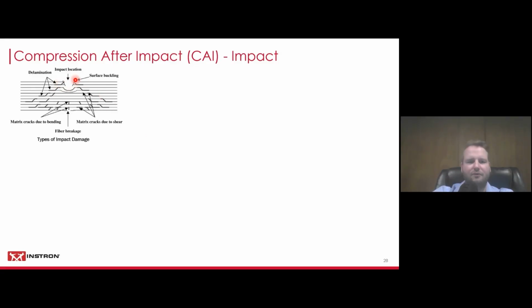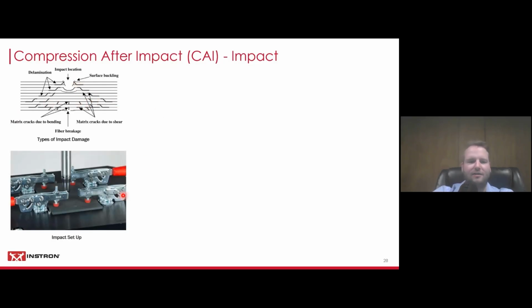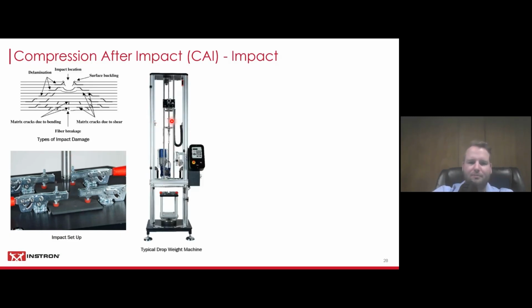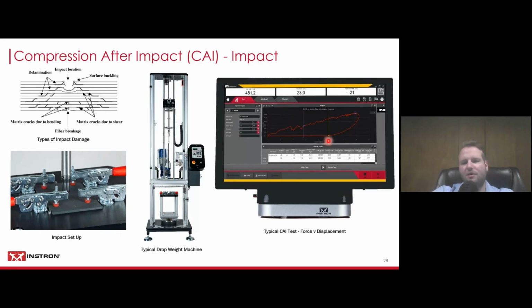So you have a failure from something like an impacting at this location. It might be visible, it might not be, but that doesn't mean that you don't have any interlaminar cracking or other kind of failures from that impact. So you need to simulate that, which typically looks like this. So you have a plate which you impact with a known force, usually done on a drop tower. So you can see here, this is the drop weight on the vertical axis coming down. And then this part down here is where your specimen is clamped. And then you impact that with a known force, which then you can record, of course, with the drop tower.